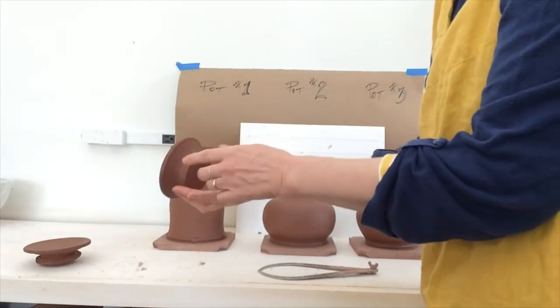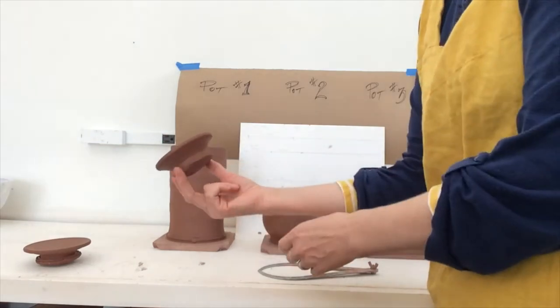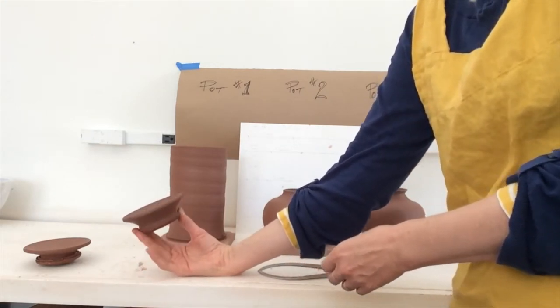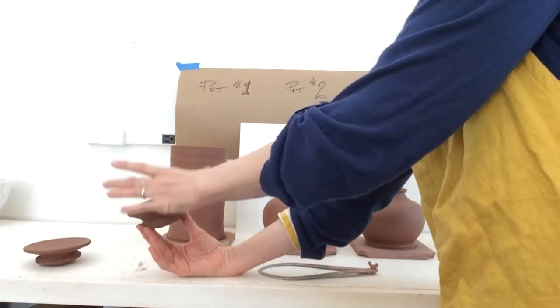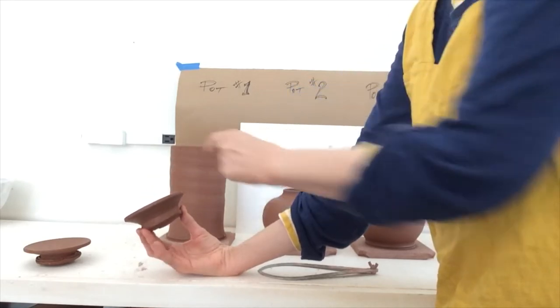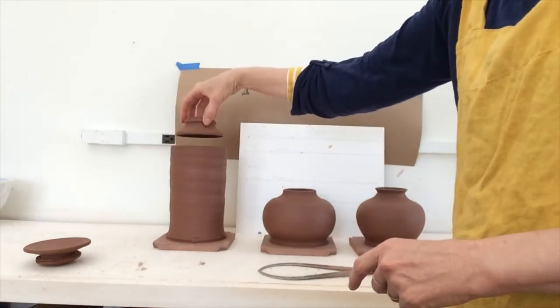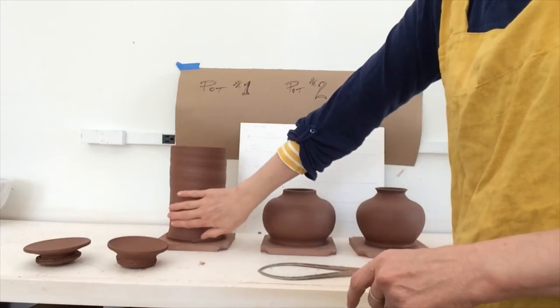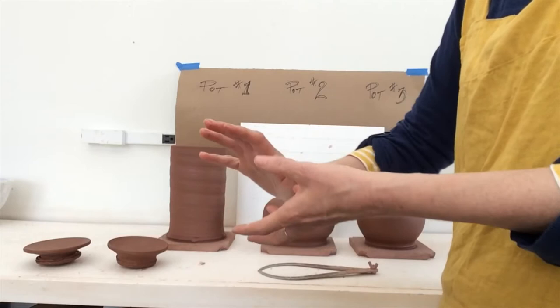This is under four inches, so I could have made it very flat and still wouldn't have to worry about it slumping. I'm also using earthenware. If I was making this in porcelain or stoneware and firing to cone 10, it's very important — if it's over four inches wide — that you make sure you've got a little bit of a curve. It's an arch that holds the weight of the knob when trimmed, keeping its shape as it's fired.